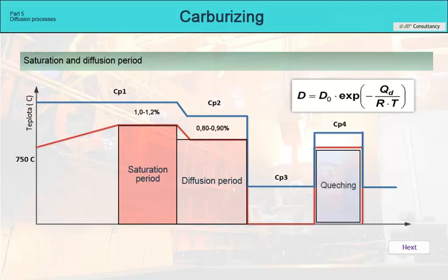In this step, the processes vary. It is hardened either directly from the carburizing temperature, from a lower temperature corresponding to the new state of the steel after saturation, or the batch is taken out of the furnace, cooled, and then heated again to the new quenching temperature. We will come back to this later. The graph shows that we change the carbon potential up to 4 times during the process. Therefore, adequate measurement of Cp and flexibility in changing it are also needed.